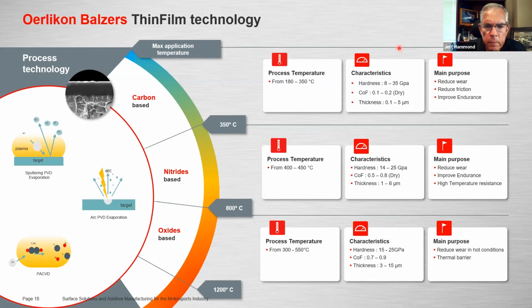So if you get deformation, it's not 3 micrometers that's going to change this deformation. You need to have a very hard substrate first that can support the load, and then the coating will just improve the wear and the friction, but not the deformation itself.